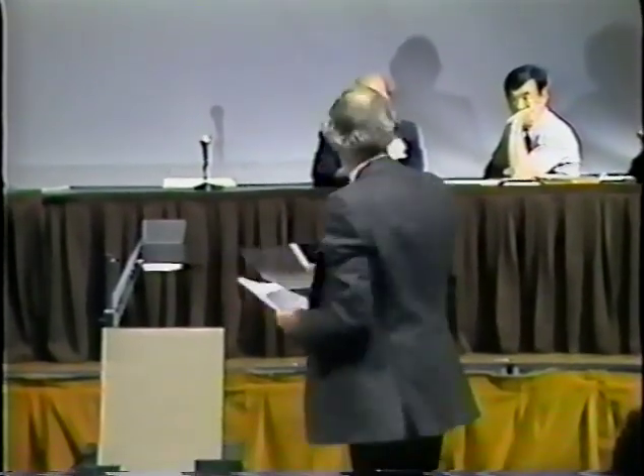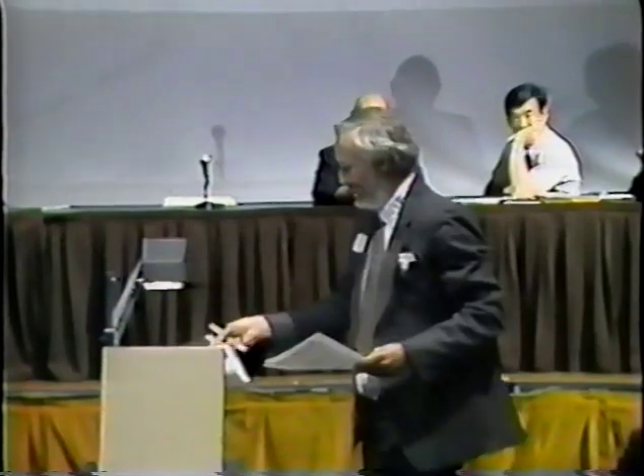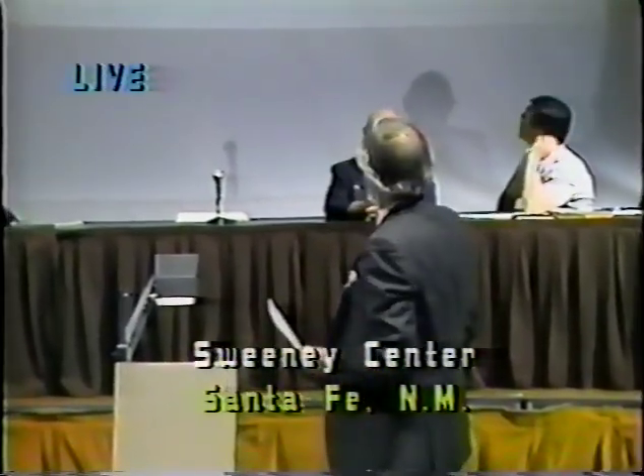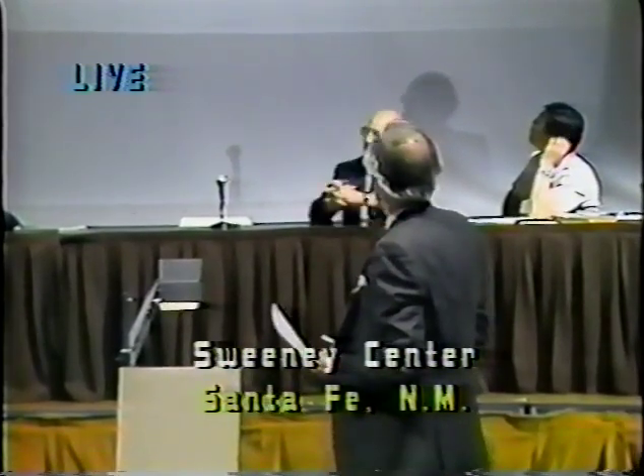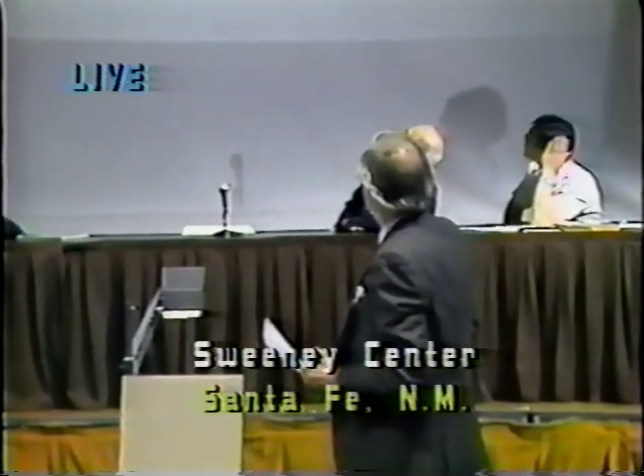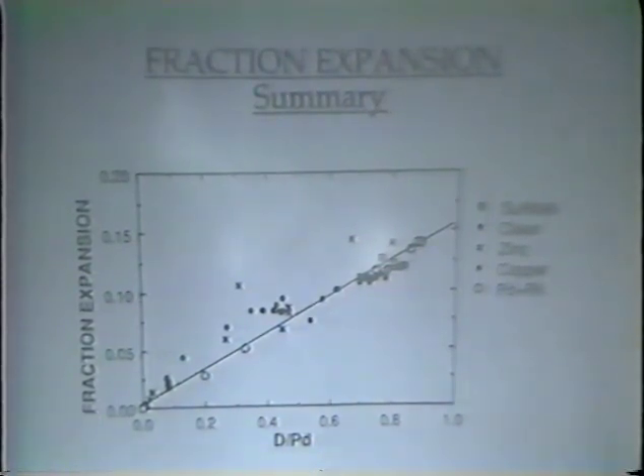And this is the last two slides right here. This one shows you the sort of overall view of the expansion. You can see the statistics are fairly good if you don't take into account those where the deuterium was extracted out. And when you reverse the current, it takes it all back out. I mean, you can get practically all of it out. You have to wait a long time if you had a lot of it in there.